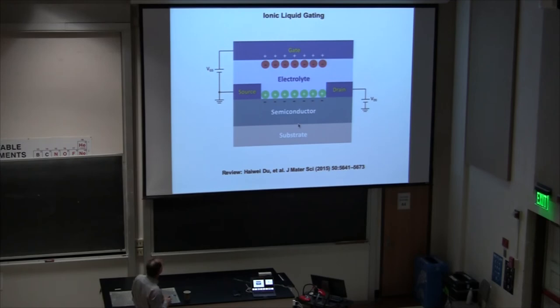The basic idea behind ionic liquid gating is you put a drop of liquid on top of your sample. This blue stuff here is supposed to be liquid. You put a gate voltage on top or on the side or wherever. If this is your positive gate voltage, negative ions in the ionic liquid go to your gate, and positive ions are supposed to sit on top of your sample. Having all these positive ions sitting on top of your sample attracts electrons in this case and it forms a conductive channel here. The idea is you can metalize your semiconductor and form an FET and get higher carrier densities than you could with just, say, a dielectric gate.